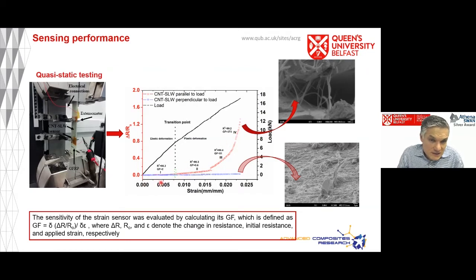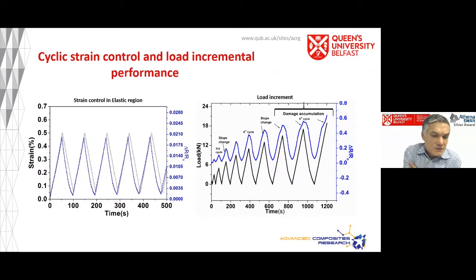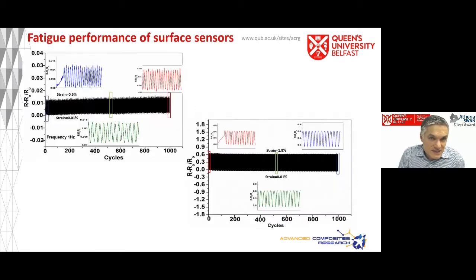What we do find obviously is that there is a change in gauge factor as you move up that loading. This is more of the same really, looking at the difference when you load your strain sensor within an elastic region and when you then go beyond that and start loading in a regime which is inducing damage, and you can see that we capture that quite well. Again, as surface sensors, the response is very fast, so we can capture fatigue performance also.